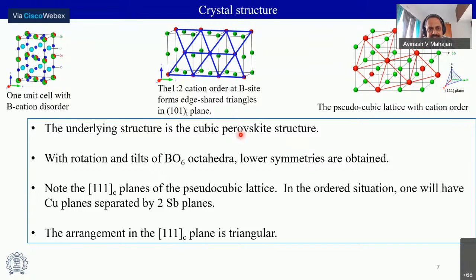However, in the present case, the B site, we are talking about Sr3CuSb2O9. So the B site is populated by Cu and Sb. And because the Cu and Sb ions are quite different in ionic size, it turns out that one can get this 1:2 cation site ordering at the B site. So in a crystal structure, you have copper occupying one site next to Sb, Sb, then copper, Sb, Sb, etc.